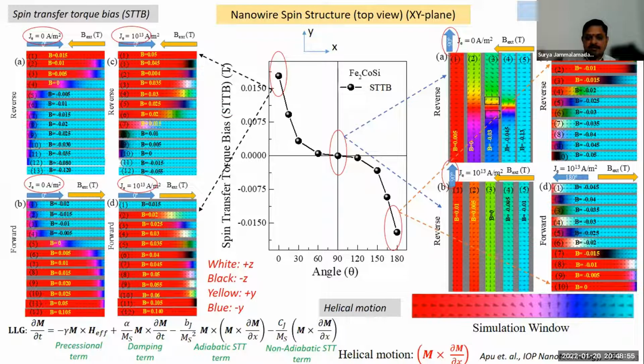So suppose if you look at the non-adiabatic spin transfer torque term, which is basically m cross dm by dx, the magnetization is always in the positive x direction. The magnetization is in x direction, that means in the i direction. The dm by dx, if it is in the k direction, Z direction, so the resultant will be m cross dm by dx in the j direction. Now again, i cross j will be in the minus k direction, and so on. So the direction of the spin which exists in the domain wall will keep changing. And as you supply the spin transfer torque term continuously, there will be motion of the domain wall. And as a result of this domain wall resistance, there will be spiral motion for the spin, which leads to the shift of the magnetization loop on the magnetic field axis.